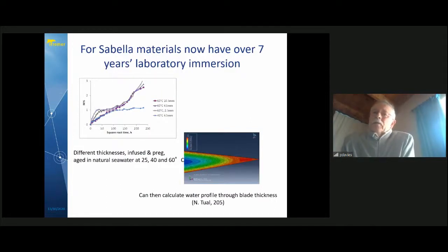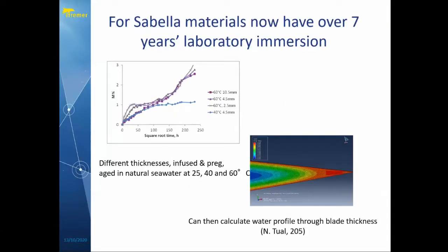So this, with the Sabella, we have materials now which have been over 7 years immersed in seawater. These include materials with different thicknesses. We have the materials which are on the Sabella D10 blade. We have the infused materials, pre-preg materials. We have materials at different, I think we go from 2 up to about 11 millimeters in these cases. And we have different temperatures. And that has given us a really big database of immersion aging for these kind of materials.